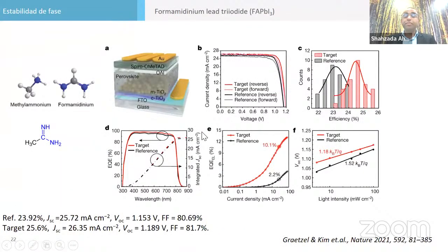Most people now also realize that MAPbI3, the first material we worked on, is not stable enough because it changes phase from one phase to another at 80 degrees centigrade. FA is more stable. So now the community is making a big push toward FAPbI3, because its tolerance factor is also high.